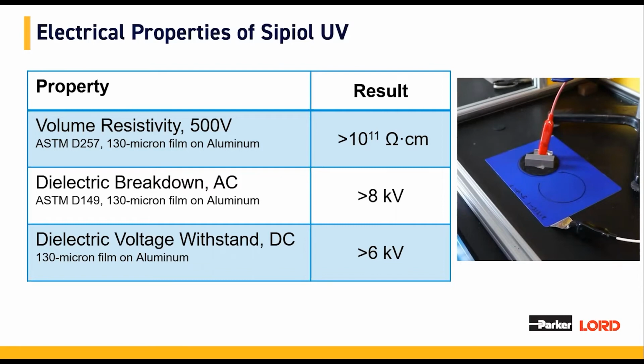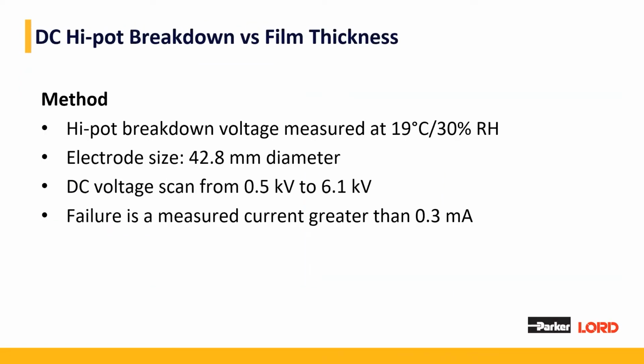Another common test is dielectric voltage withstand testing, sometimes referred to as hypot testing. It is measured via direct current. The coating can achieve greater than 6 kilovolts of applied voltage with minimal current leakage. We are often asked for film thickness versus electrical performance of Sipiol UV. The next few slides show this data for hypot testing and dielectric breakdown testing.